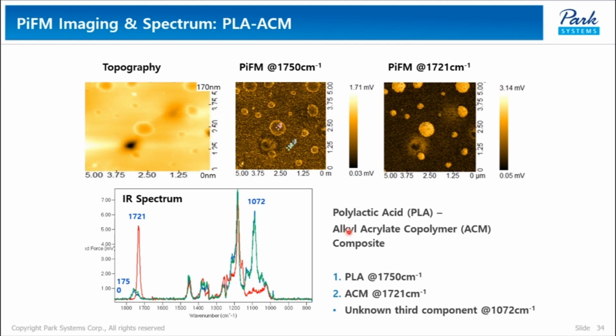One of the possible candidates for improvement is the nanocomposition of PLA with an alkyl acrylate copolymer, ACM. The sample has been studied using PIFM to determine how the materials are dispersed. Using the excellent correlation between PIFM and the FTIR spectra, we are able to confidently show where the two materials are located within the material matrix with nanometer spatial resolution.